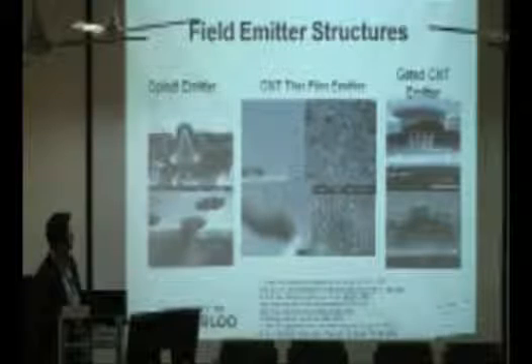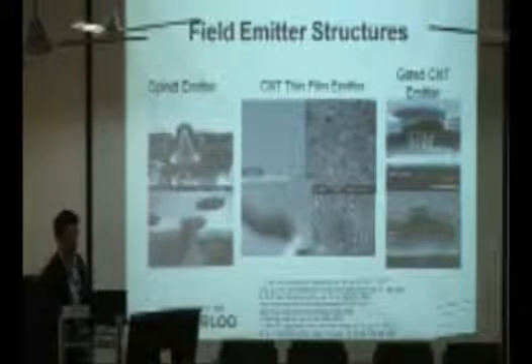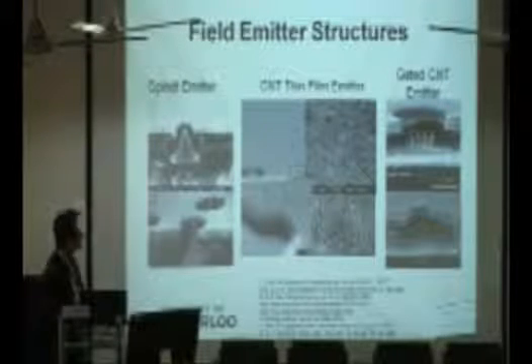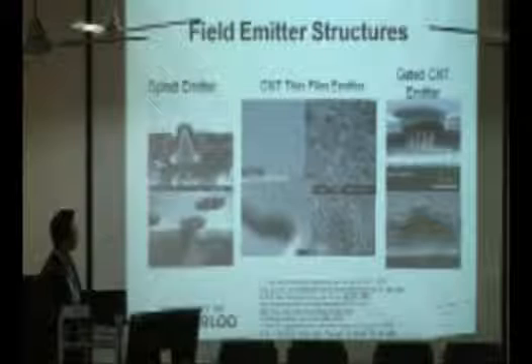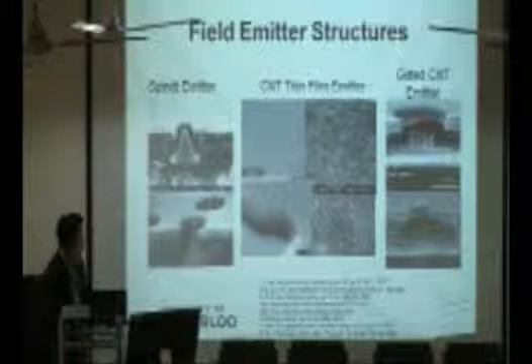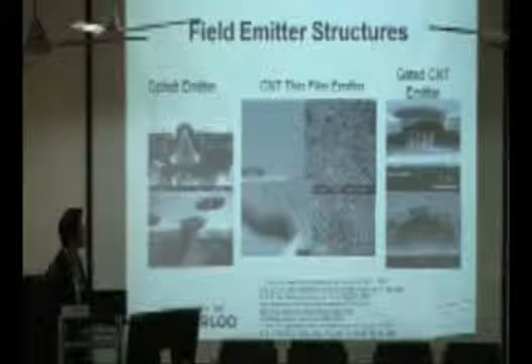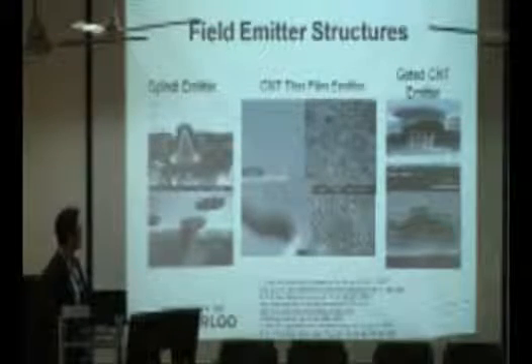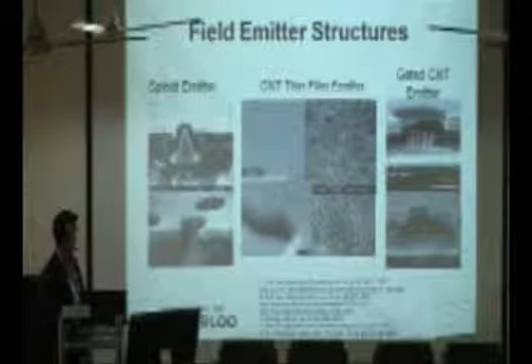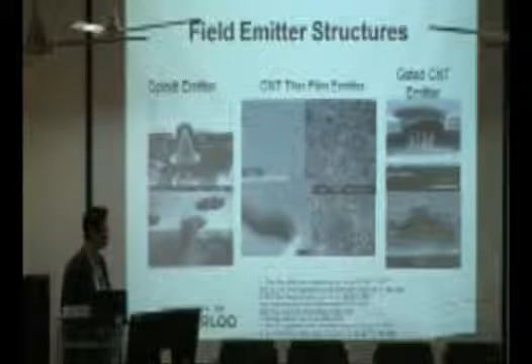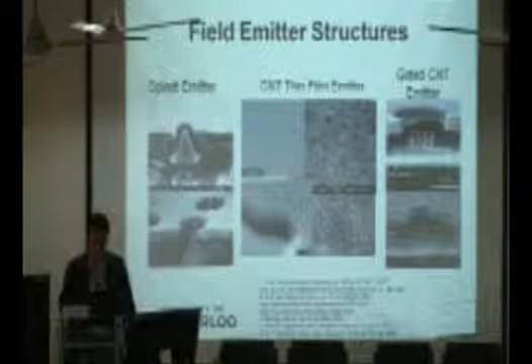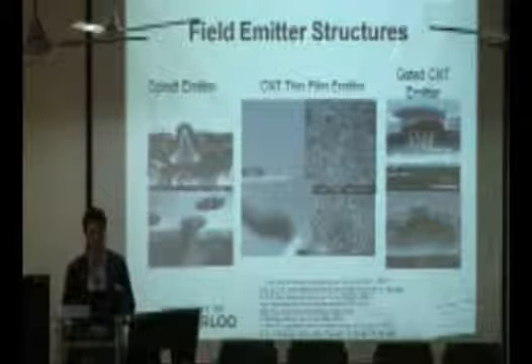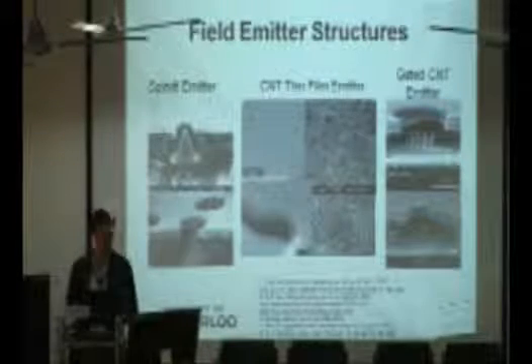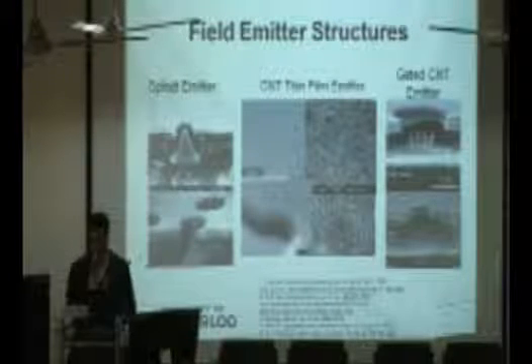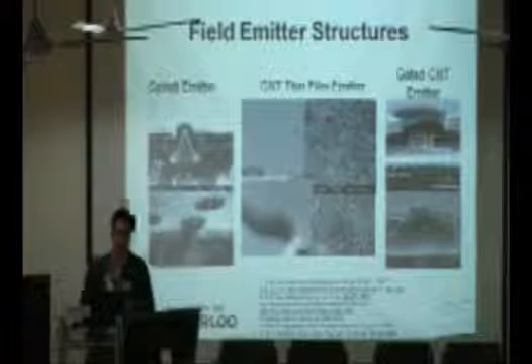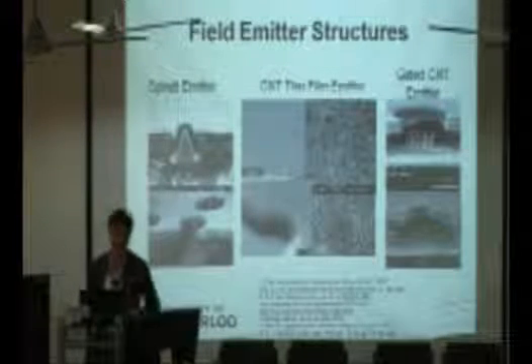The second material we have looked at is CNT thin film emitter. We have looked at sparsely distributed vertical carbon nanotubes as thin film emitter. We have looked at randomly aligned emitters for field emitting. We have looked at densely populated vertically aligned carbon nanotubes for emitters. We have also looked at just random distribution of vertically aligned emitters. So the reason that we have looked at different morphology of CNT as well as different architecture is really to increase the lifetime as well as the current stability.